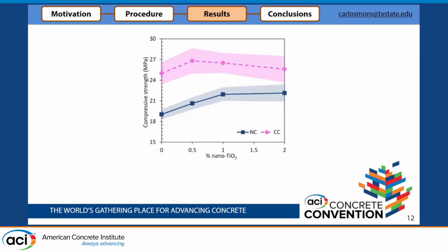Our hypothesis on that is that the porosity reduction that happens during the CO2 capture basically blocks the beneficial effects that these nanomaterials could have, because of the dual porosity reduction happening because of the nanoparticles, but also because of the CO2 carbonation during the chamber. Okay?